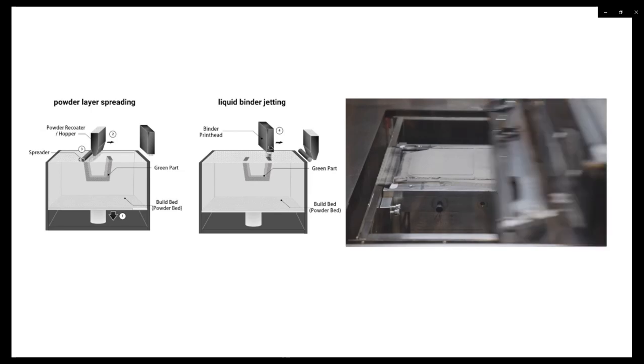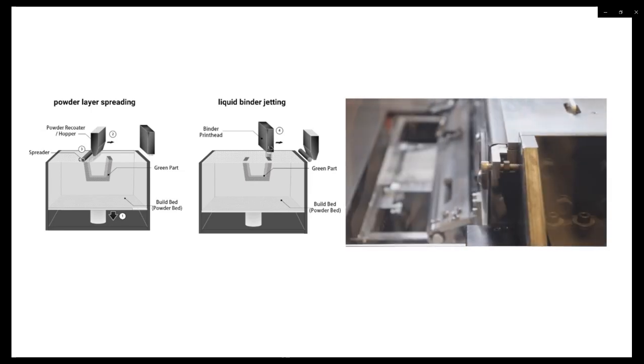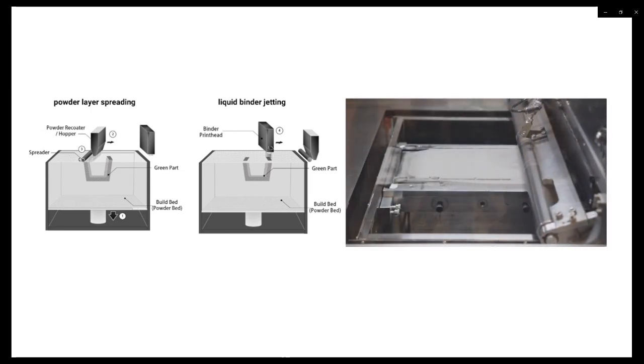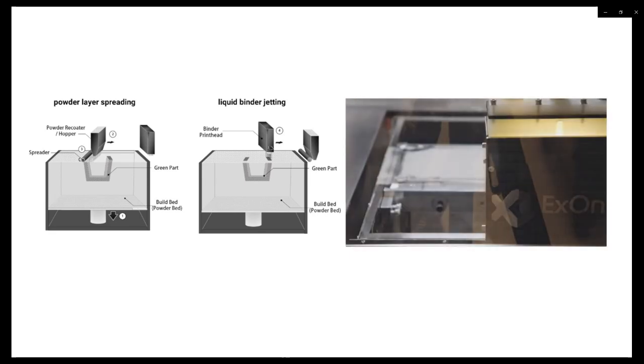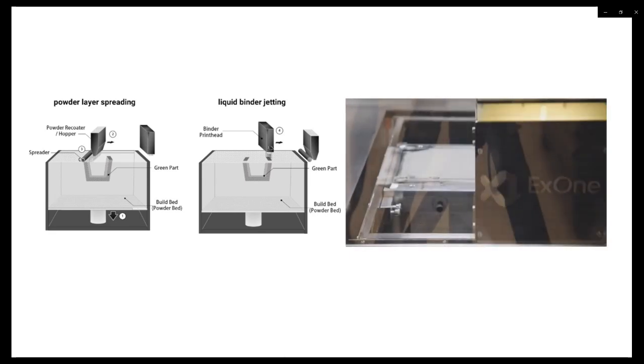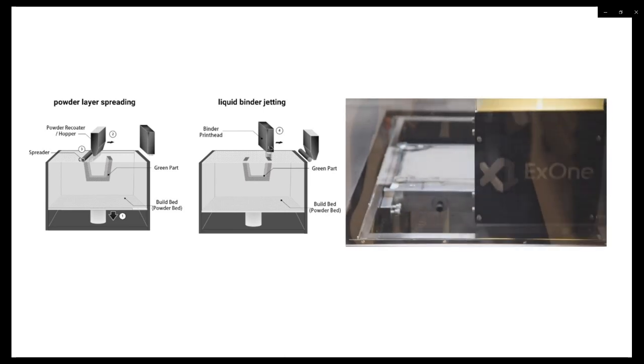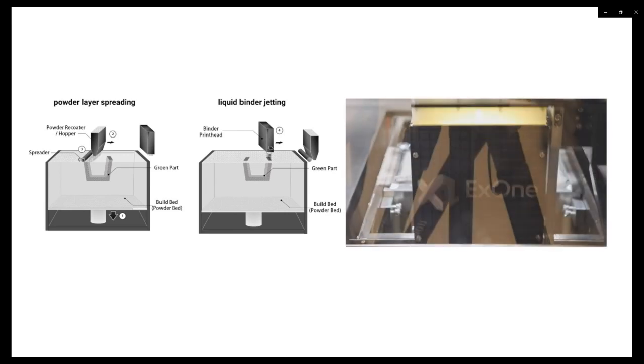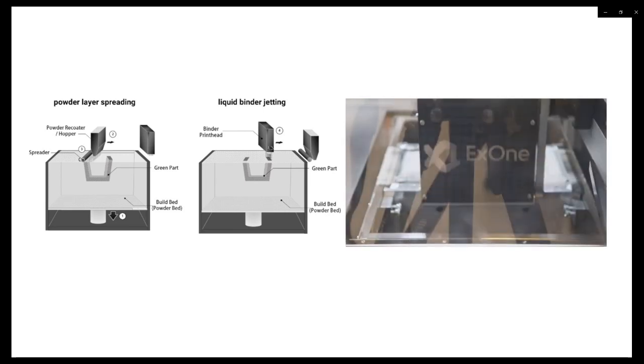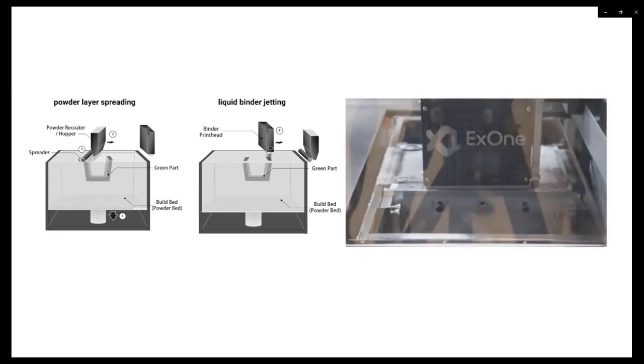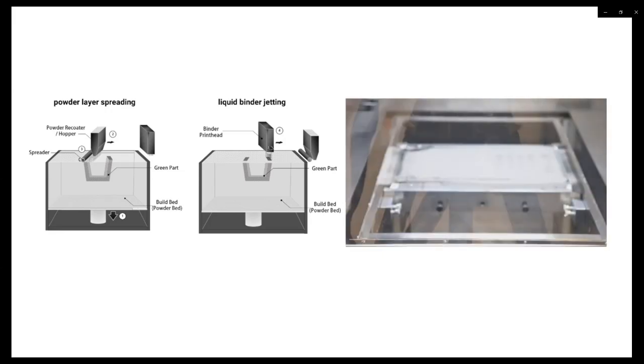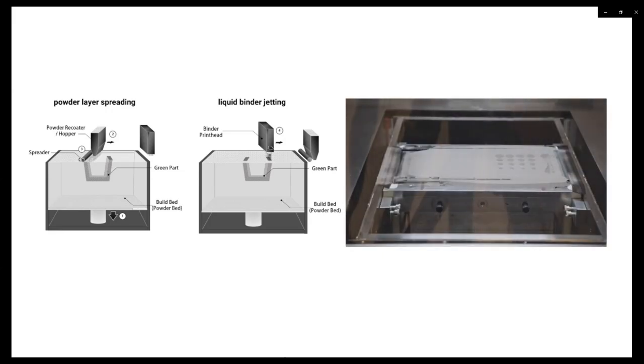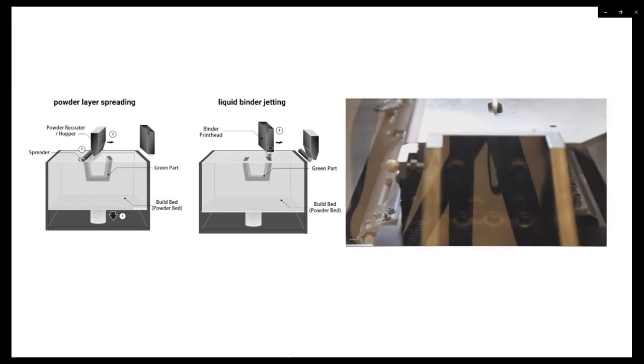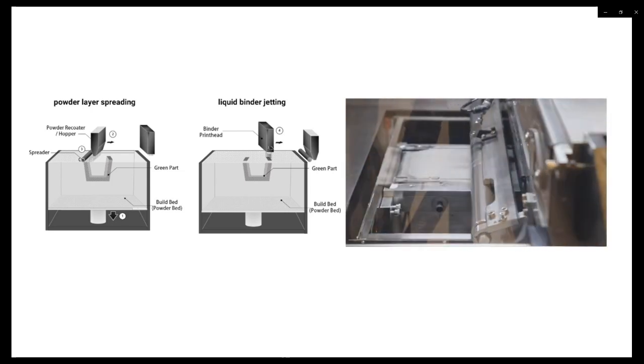In binder jetting additive manufacturing, the principle behind part fabrication relies on the sequential spreading of thin layers of powder, which is done using a roller, where a typical layer thickness is in the range of 50 microns. This is followed by selective jetting of a liquid binder or glue using a printhead. The printhead jets the binder at the location corresponding to the part slice being printed. This process is repeated until the final geometry is complete.